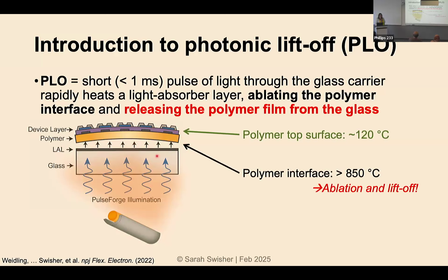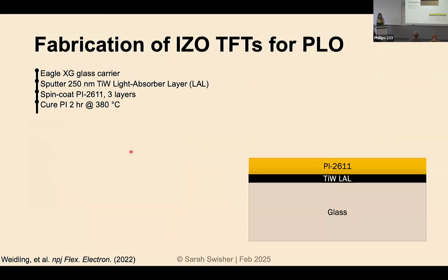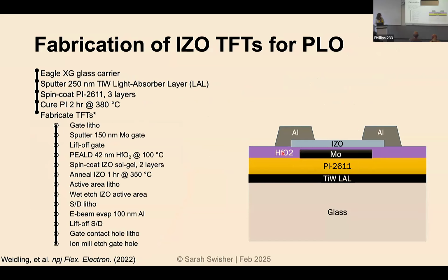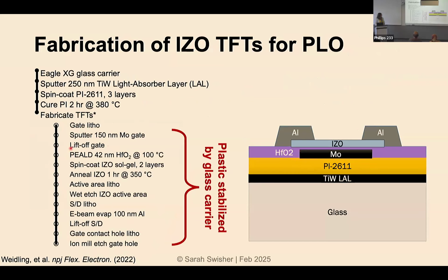And then the nice thing is that this substrate can be used over and over. It doesn't ash and it doesn't produce a bunch of carbon on this surface or anything, so we can actually just use that glass carrier over again. So the device fabrication, we start out with the light absorber layer, and then we spin on our polyimide. We cure the polyimide, and then we fabricate the TFTs. So this is the same structure that we did before. We use that thermal annealing method here. And all of this process is done when the plastic is stabilized by that glass carrier.